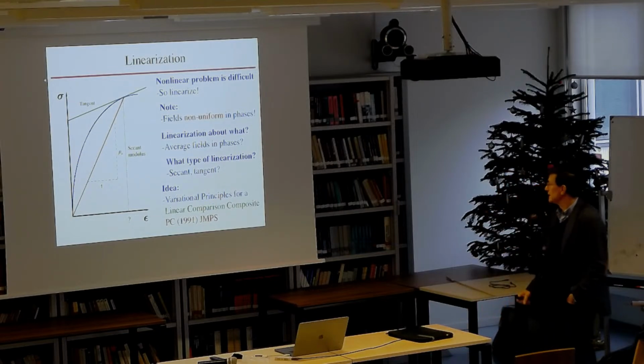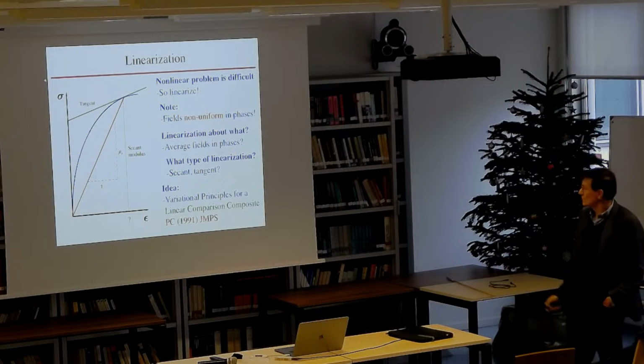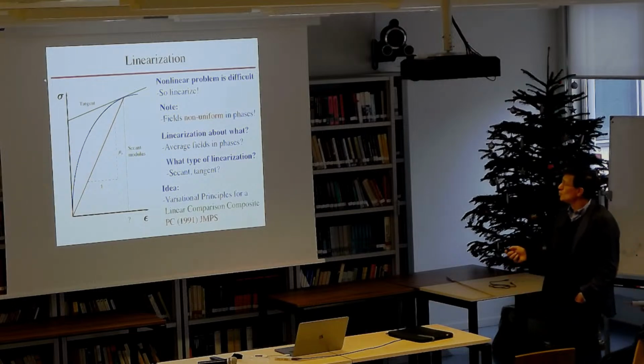Methods based on things like Green's functions and standard results from the theory of linear PDEs. So we have to think of some linearization. In this case, the material behavior that we're interested in is not weakly nonlinear. Plasticity is strongly nonlinear, so we cannot do perturbations about some small parameter. And in addition, when you have a heterogeneous material, even if the phases are homogeneous, the fields will be inhomogeneous or non-uniform in the phases.